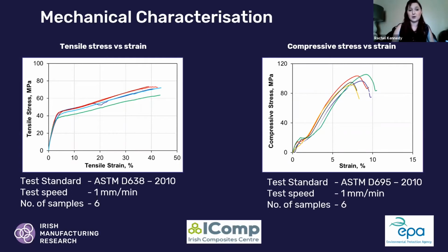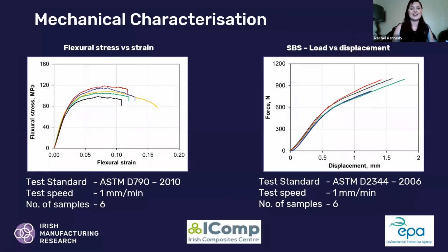The other tests we did were flexural and SBS. Flexural is another one that is standard in the technical data sheet. This is just the bending strength it has. SBS is a little bit more unusual, but we did feel it was necessary because this is short beam shear, and this is to make sure that we had good consolidation between the layers. Because we were layering it up and compressing it down, we wanted to make sure that there were no delaminations or pre-existing cracks or voids, and the SBS is one of the best ways to see that.